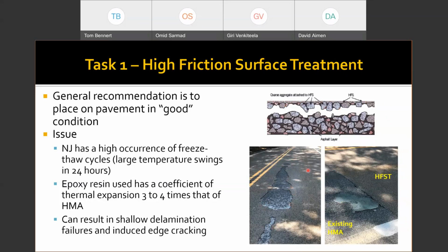What is really happening here is that as we get into these temperature cycles, especially these larger temperature cycles within a 24-hour period, the expansion and contraction of the epoxy is far greater than what is occurring in the asphalt. And if the asphalt is in the wrong condition, this expansion and contraction can basically rip the material apart. That's what you see here. You see these shallow delaminations. Even in the picture on the right, you can see where the HFST started and where the existing HMA stopped, and you can see what looks like a transverse crack right at that edge, and that's because that HFST section is expanding and contracting right at that edge. You can also see a little bit of excessive epoxy that was left on that road. That obviously is a problem as well because there's really no friction to that.